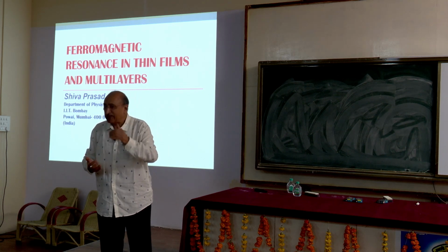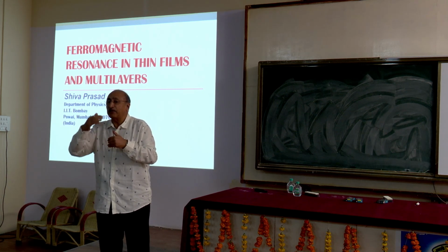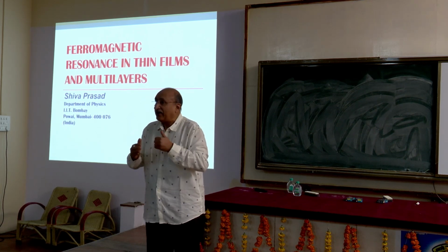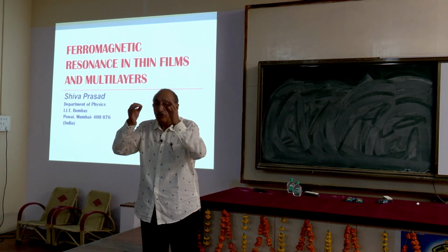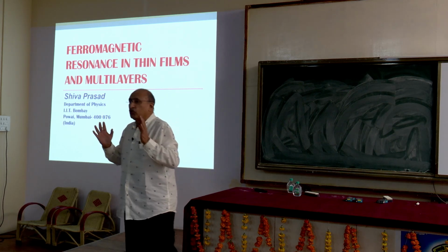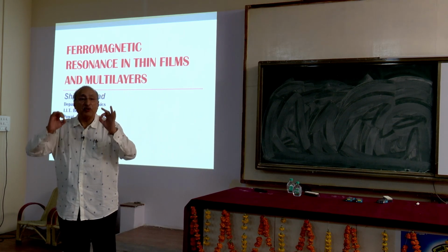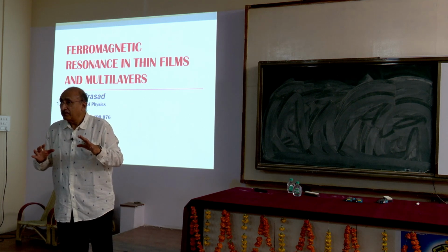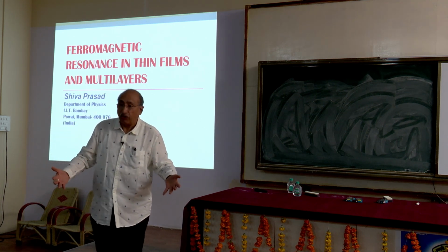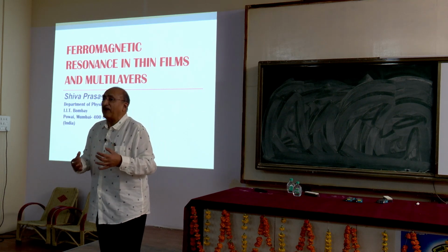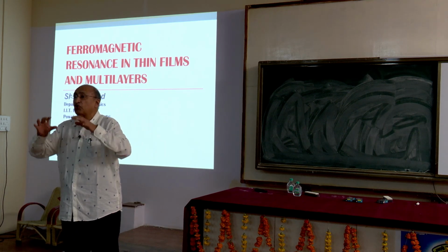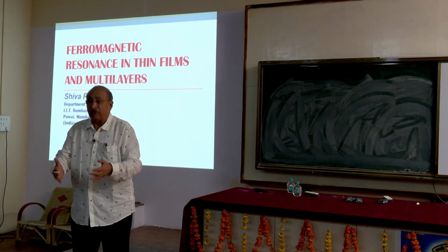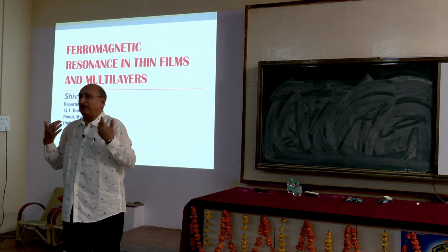So cobalt ferrite is one such case when you find that the magnetization that you calculate from experiment differs significantly from what you would have expected from the normal systematic Hund's rule, assuming totally orbital angular momentum to be quenched. All right, and this is ascribed by experimentalists who don't understand theory, let me be honest, to the fact that orbital angular momentum in this particular system is not perfectly quenched. And look here, this cobalt ion also shows a large anisotropy, which is also likely to be related to this particular fact.